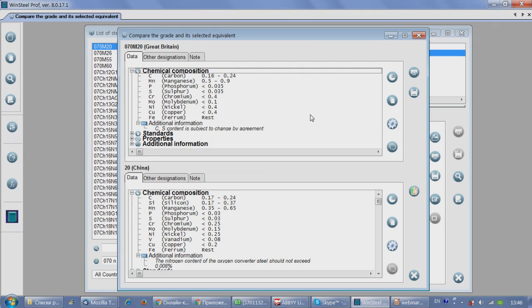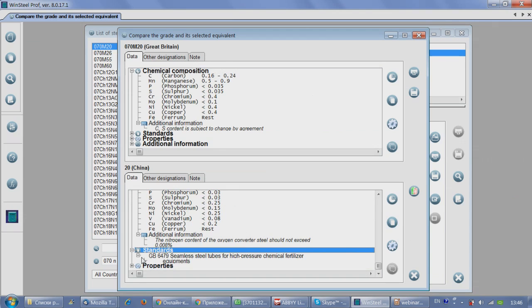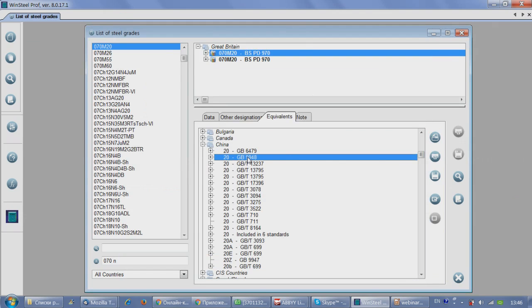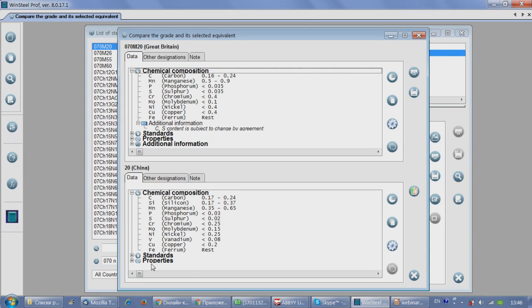And here you compare this grade and this one, with information about the standard. This standard is GB 6479, a standard for tubes, for example for high pressure. And maybe this other standard, which is also for tubes. I don't know which application you need. Maybe sheets and strips, if you need those. For sheets and strips it is better to use this grade, and you may see that the compositions are similar.